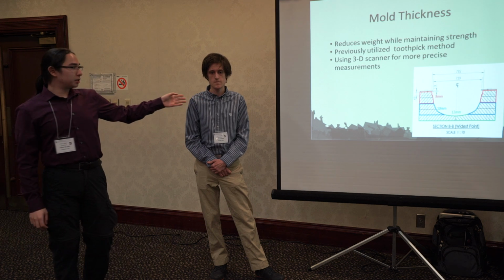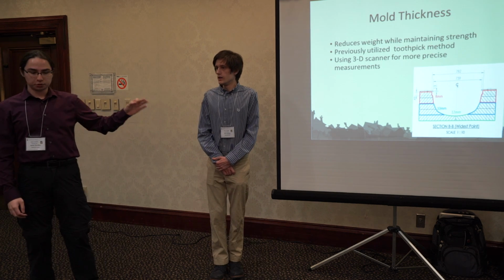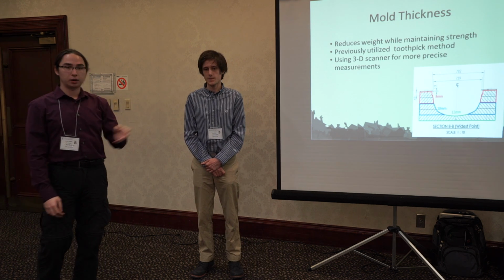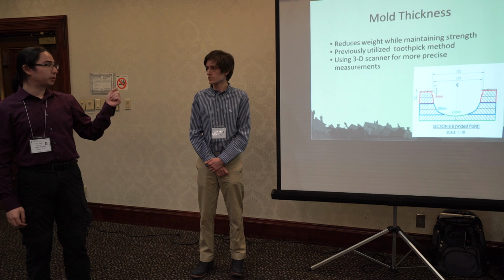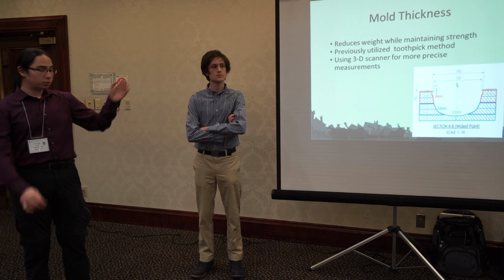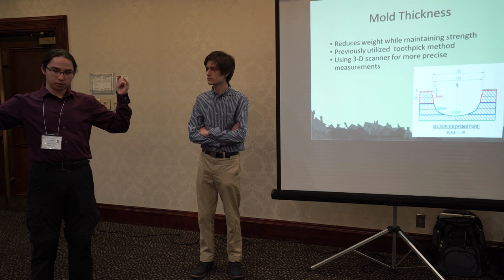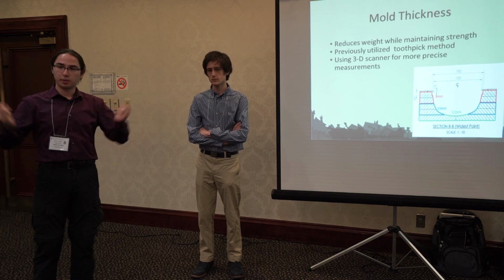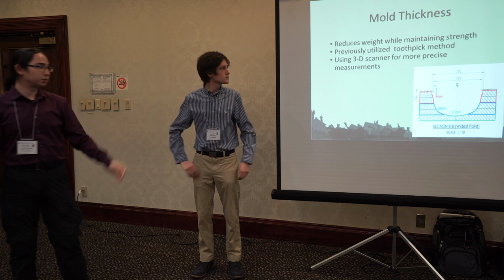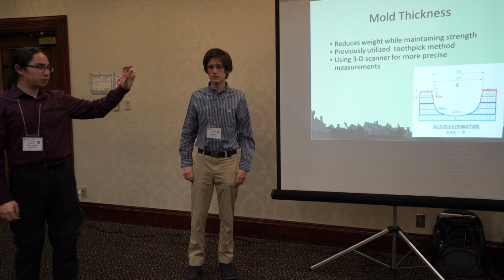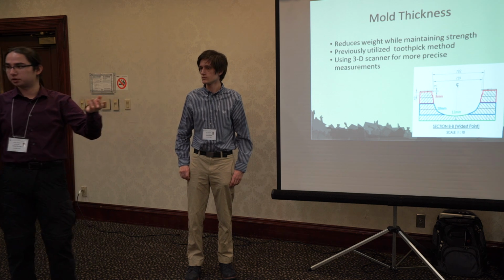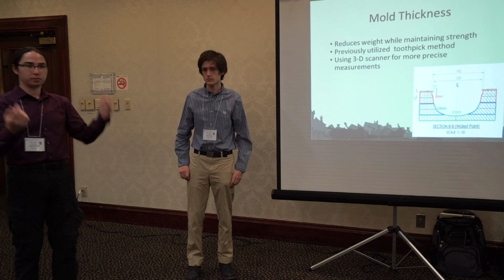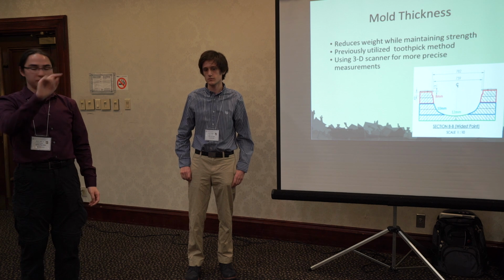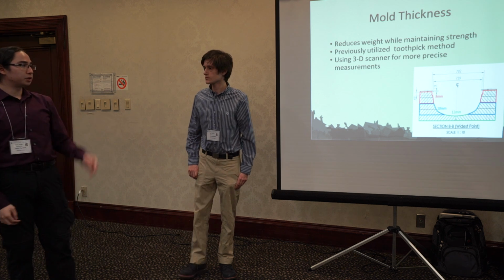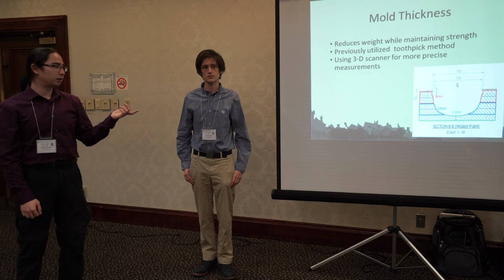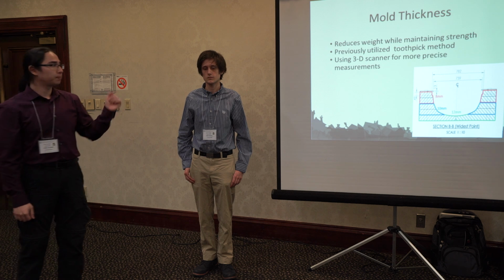As Dale mentioned, with having to maintain structural integrity while removing the ribbing, we've decided to do a variable thickness along the bow of the canoe and the cross section. In the areas of the canoe where structural integrity is not as required, such as the top, we've made it thinner, and we've made the base thicker going down. So this saves both weight and increases the strength.